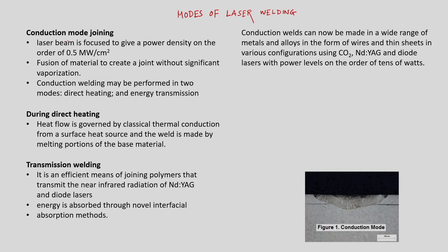The first mode of laser welding is conduction mode. In this mode, we are using a laser beam focused on the work part, generating a power density up to 0.5 megawatts per centimeter square. When we generate a power density of about 0.5 megawatt per centimeter square, we are generating conduction mode of joining.